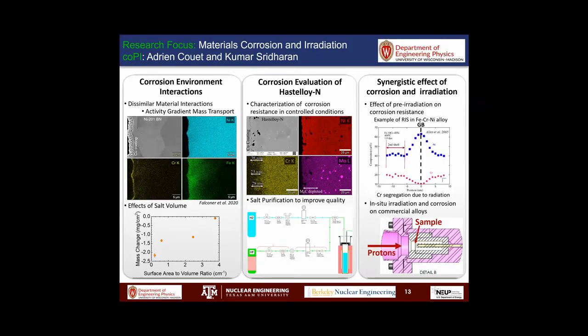The group at Wisconsin is looking at the interactions between test samples and the test environment. It's crucial to understand how those behave from a static corrosion test. Some of the results include the strong effect of a dissimilar material that can lead to mass transport in the salt system. For example, when nickel 201 is placed in a crucible of stainless steel 316 and we make sure that no galvanic couple is present, there is a significant mass transport of iron and chromium from the crucible to the nickel samples. This can have important implications on how one designs a corrosion experiment for an MSR.